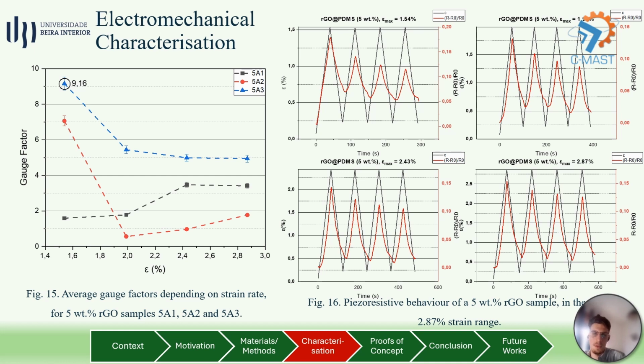Lastly, 5% samples had the highest sensitivity, reached a maximum average gauge factor of 9.16, explained by a more saturated conduction network that may have sacrificed the composite's flexibility. Even so, the acquired signal showed us high linearity and amplitude, although the relative electrical resistance leakage persisted.